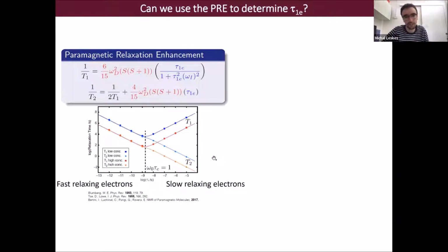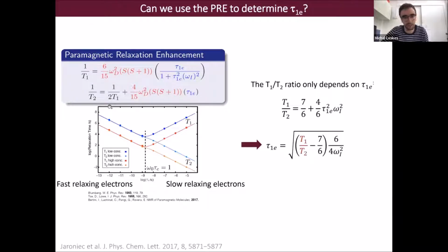We can show this also mathematically just by dividing one equation by the other, and we see that with this approach, we are able to obtain the electron relaxation time just from the T1 and T2 values, just from the ratio of them, and the nuclear Larmor frequency. But this is a quantity that of course we know. So in the next slides, we're going to use this equation as a tool to try to understand the NMR spectra that we observe.